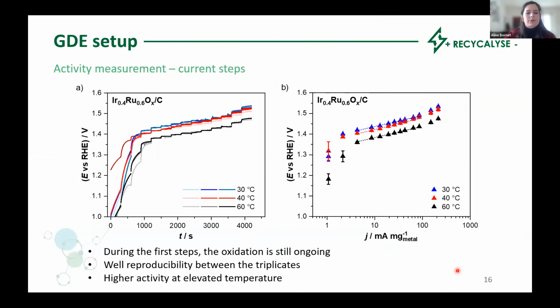And so we use this electrode in our GDE setup, and we tested the performance of the catalyst first in terms of activity. This was done by stepping the current at different values every 5 minutes at 3 different temperatures, 30, 40, and 60 degrees. Moreover, for each temperature, triplicates were measured to ensure the good reproducibility of the experiment.